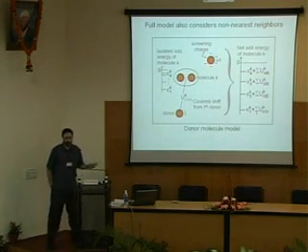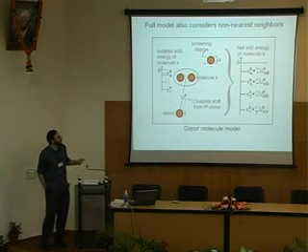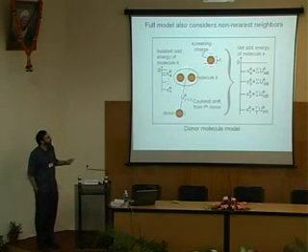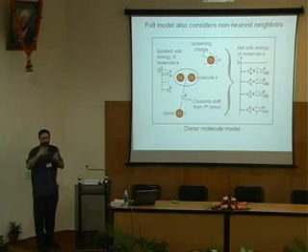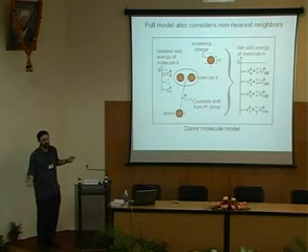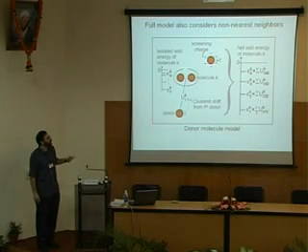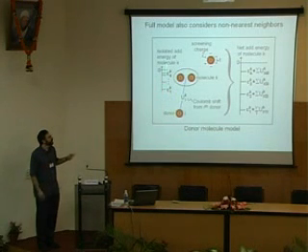Before I show you the data and comparing the model to the data, we add one more thing, and it's very important. Every one of these molecules has its own particle in the box energies, and that's what Professor Harrison calculated. But we also put in the fact that there are other donors that are farther away. Those donors do something. They don't change qualitatively the way that the energies look like for this particle in the box. They won't increase the number of electrons that you can sit over there. This dopant's too far away to do that. But it basically shifts it up and down. The Coulomb attraction or the Coulomb repulsion shifts this box up and down.